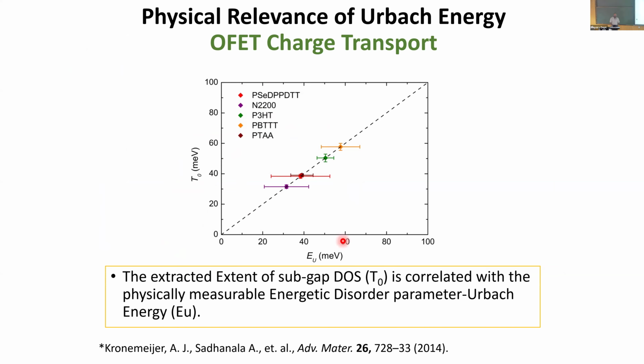What we find is this T-naught, which we measure for most FETs, where we try to estimate the subband gap density of states, which basically determines the mobility of carriers inside the semiconductor. So you want to minimize this. Hence we want to measure mobility and sub-gap density of states and say, okay, how can we improve on this, right?